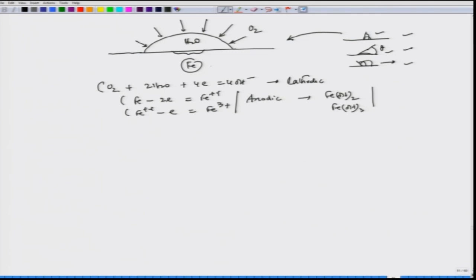Now, due to the reaction, this oxygen is getting consumed. So, once we have consumed oxygen, then of course, from this plane to this particular center position, we have a concentration difference. Why is that concentration difference coming? Because the oxygen that is being consumed here or here is getting replenished by the oxygen diffusion that is coming from air, because these peripheral sections are under direct contact with the air.